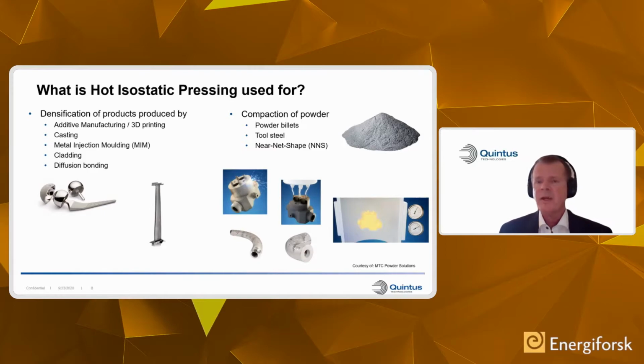Typically today, two areas for the use of HIP, obviously densification of products, added manufactured products, of course, castings, MIM products, claddings, and diffusion bonding. I would say that the biggest usage of HIP today is probably the consolidation of casted products. Also, a fairly large area is the compaction of powder, which is basically starting from a powder as raw material, which is then filled into a pre-designed can. The can is evacuated and sealed, and it's hipped. You can have any type of geometry, from the powder-based billets, which basically are rectangular or cylindrical, to the near-net shape products, which in shape and design very much resemble the end product.